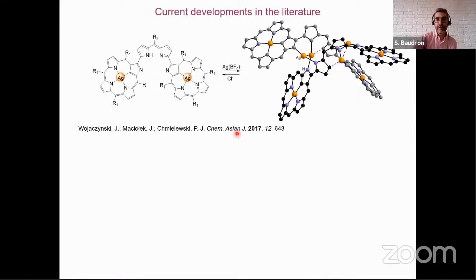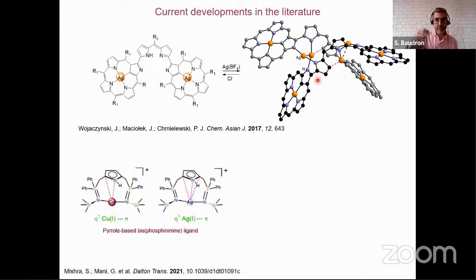So before I conclude, I would like to highlight some recent examples from the literature involving this silver-pi interaction with pyrrolic compounds. There is this very nice work by a Polish group where they prepared a dipyrrin bearing at the alpha position a confused porphyrin. Upon assembly with silver tetrafluoroborate, they observed a rather complex architecture with silver-pi interaction of a dipyrrin fragment. Also, there is a very recent report published online about two weeks ago by the group of Mani with a pyrrole derivative bearing a bis-phosphinimine ligand. Upon complexation of copper(I) or silver(I) cations, they observed an interaction in this case of the silver with the carbon-nitrogen bond, unlike what we had observed in all our examples.